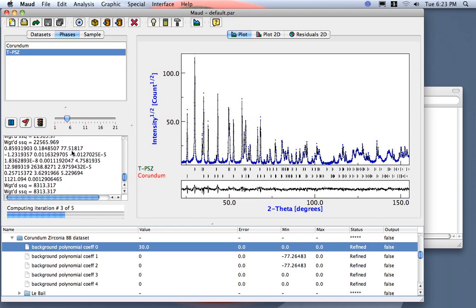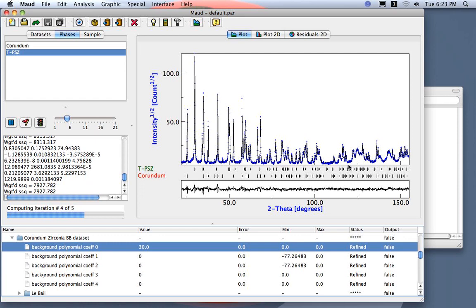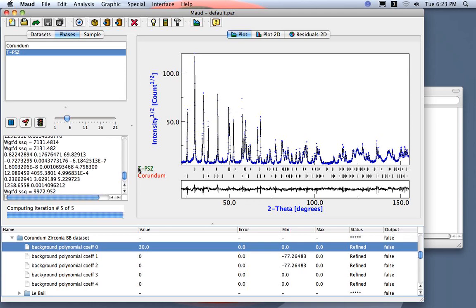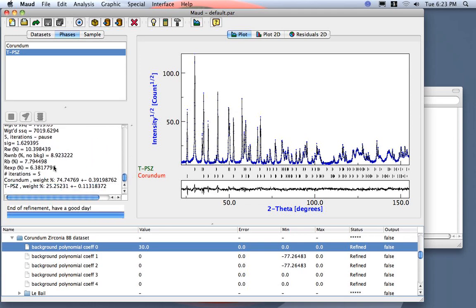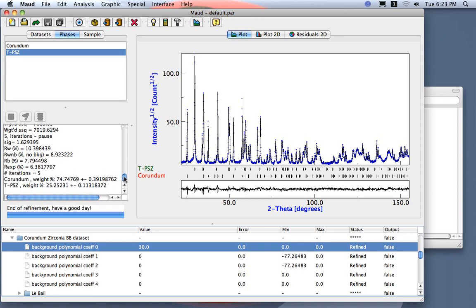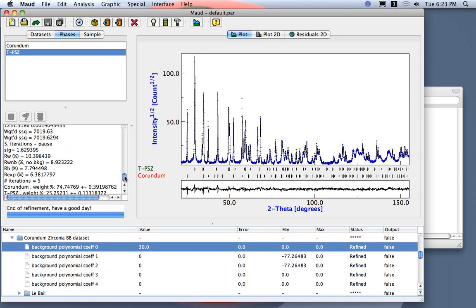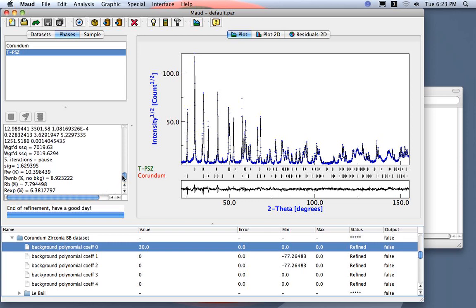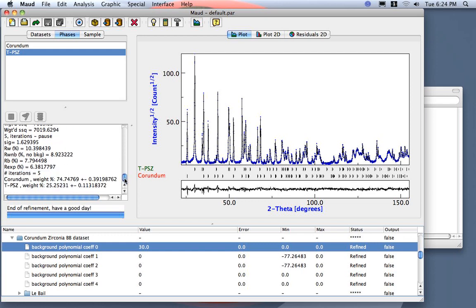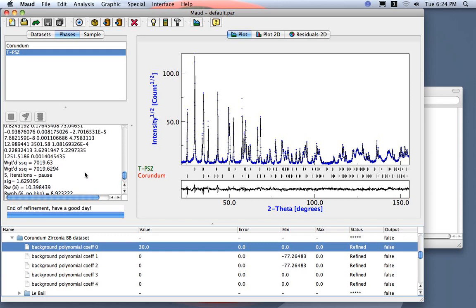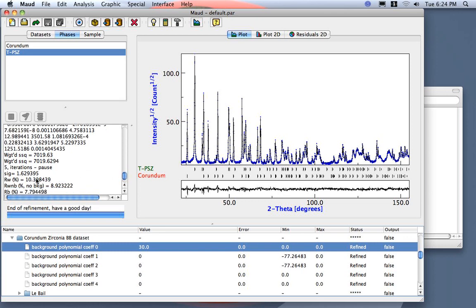Now we can check the progress over here. You see the fitting is going better and we are nearly to the end. Here it is. We actually have 74, nearly 75 percent and 25. I can say to you this was a mixture made exactly with this quantity, so we get exactly a good phase quantification. And here are the RW, it's just 10, and the goodness of fit 1.6.